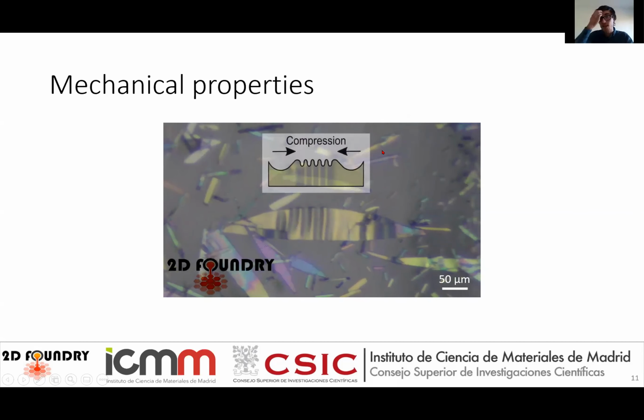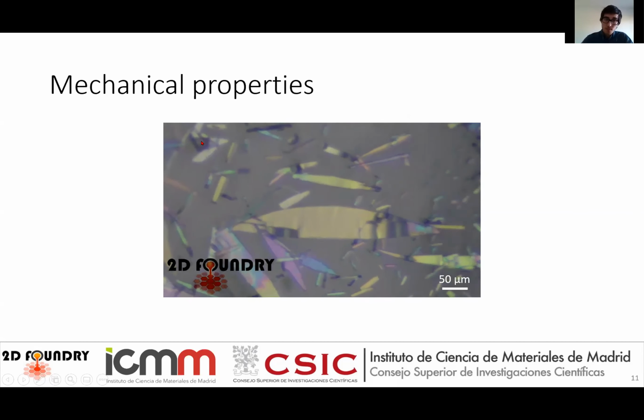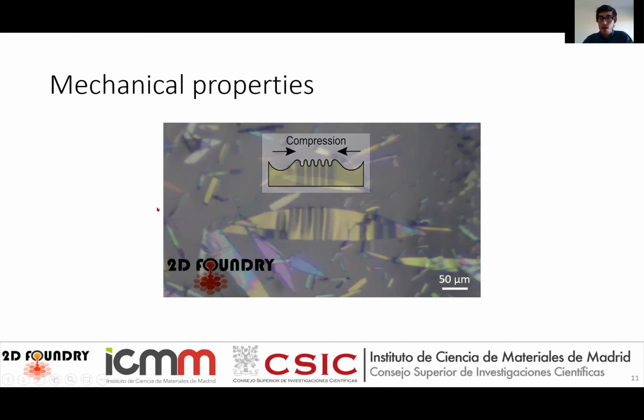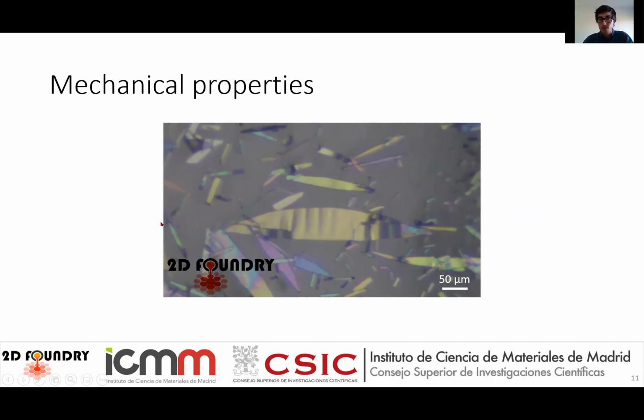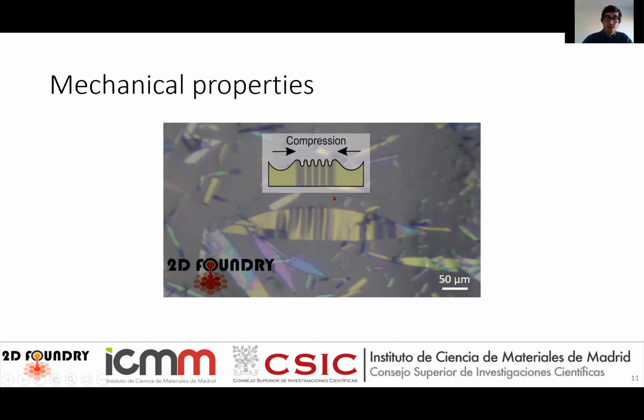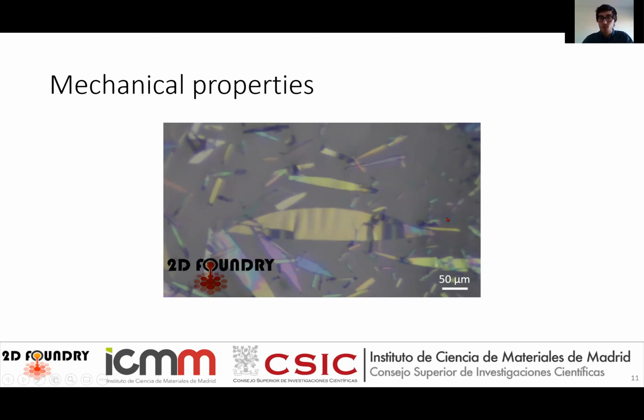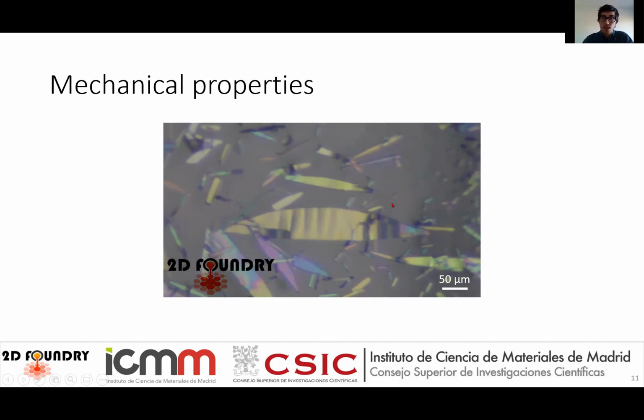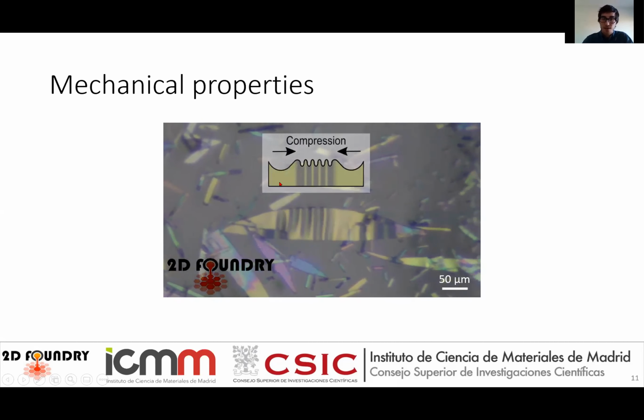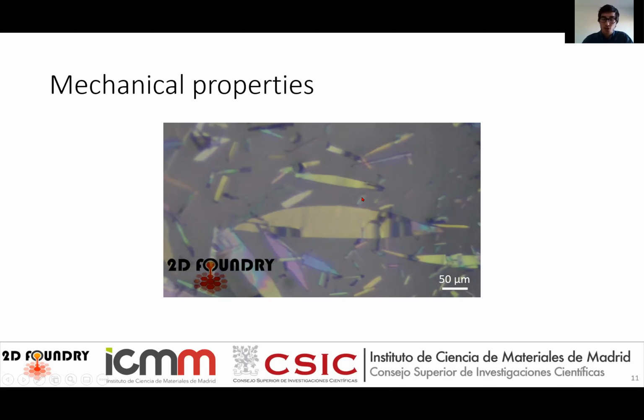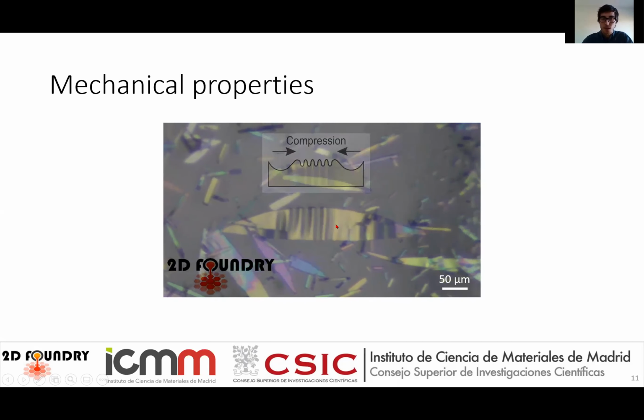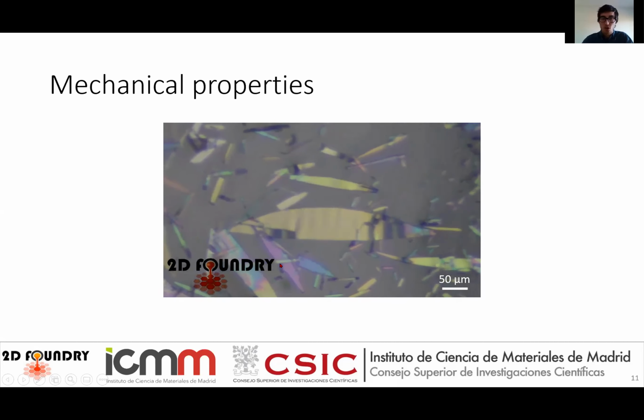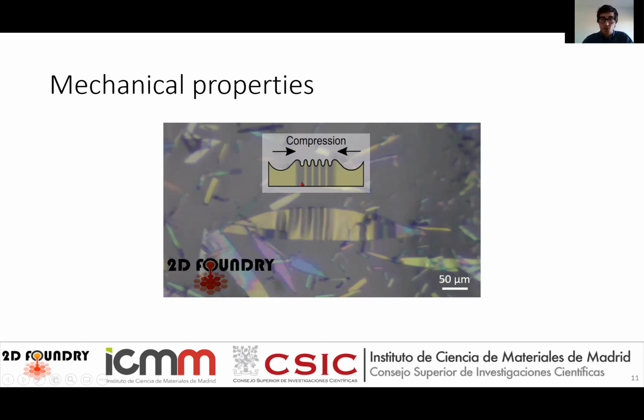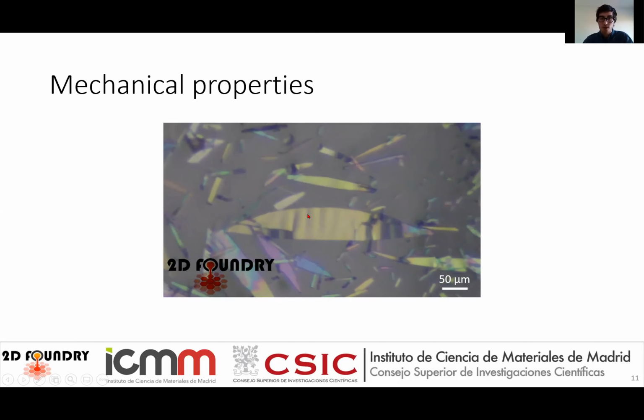Also, we have studied the mechanical properties. We have studied them with the buckling metrology method, in which we place the molybdenum trioxide flakes onto a PDMS substrate, and we compress it with a glass. We compress the PDMS, and as you can see, these ripples create peaks in the flake. This is the color of the rest of the flake, and in the valleys you can see a darker color.